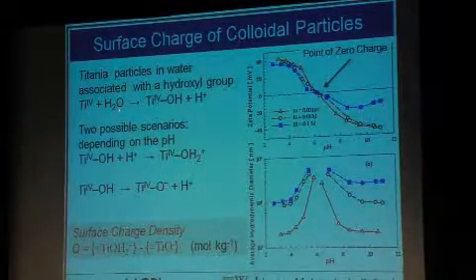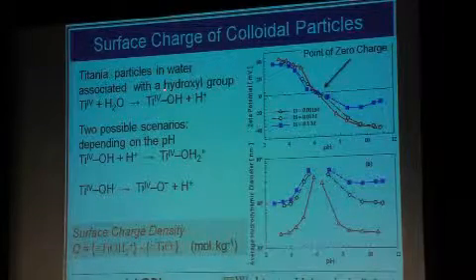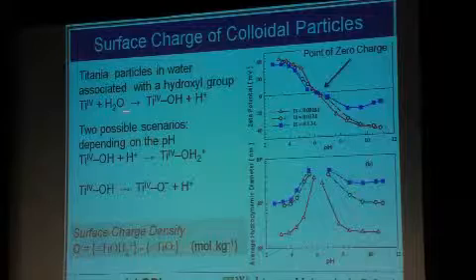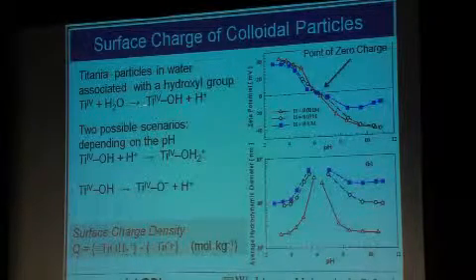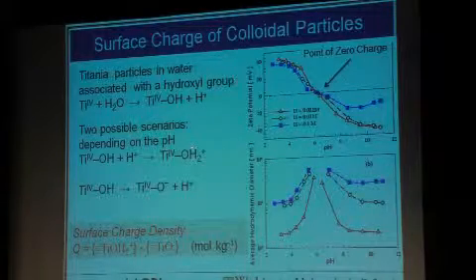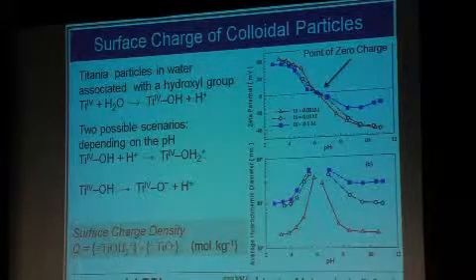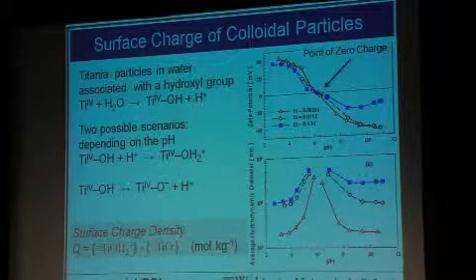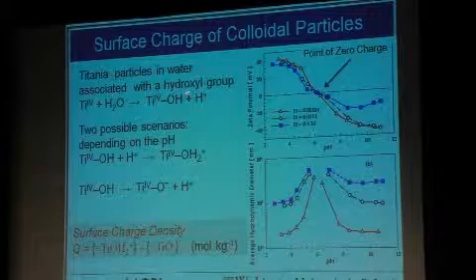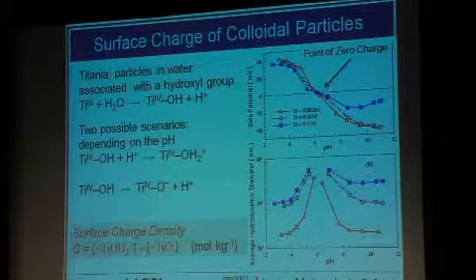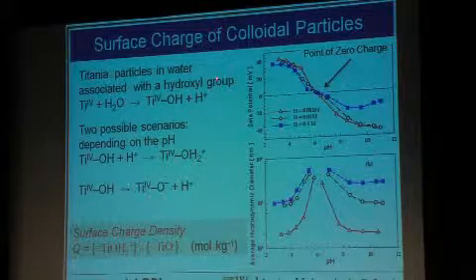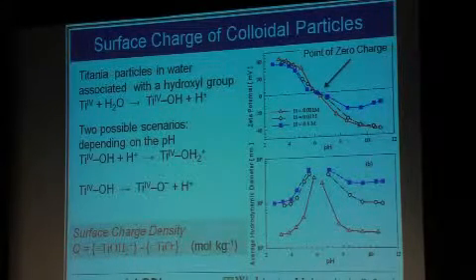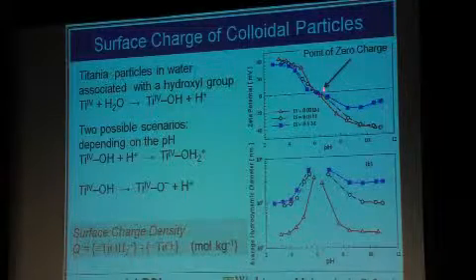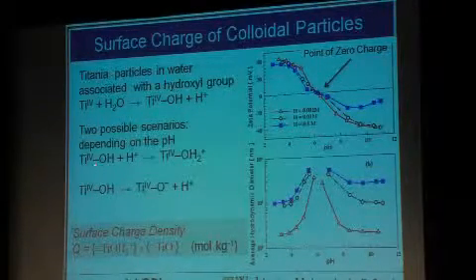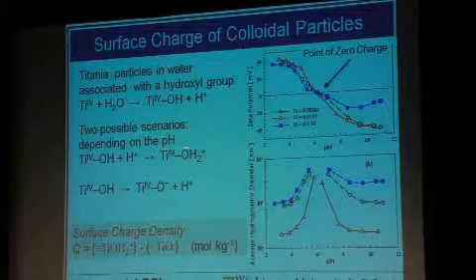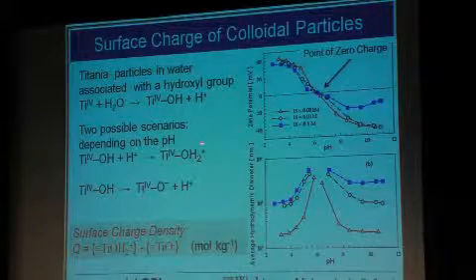So I take a TiO2 material, just throw it in water, and hydroxyl groups attach to it. There is a certain equilibrium that is established. Now, this is clearly a surface area driven process, right? So you might think, oh, this is good for all TiO2, and I put it in water, I'm going to end up with a certain pH. As I'm going to show you very soon, depending on the size, the amount of free hydrogen ions, which is of course reflective of the pH, is going to be different, and you're going to end up with different pHs. If the pHs are different, the point of zero charge. Now, once this happens, the Ti and OH, depending on the pH in the system, also speciates into these two. This is a positive charged complex.